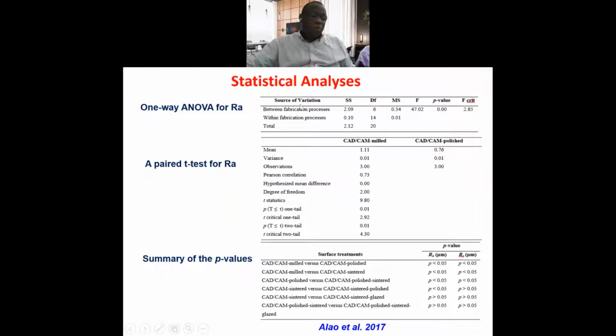So I used one-way ANOVA in order to understand the effect of the fabrication process on the average surface roughness. You can see when the p-value is less than 0.05, that means the fabrication process has a strong effect on it. So I also used a post hoc test to find out the effect of one fabrication process on the other. And these are the results.